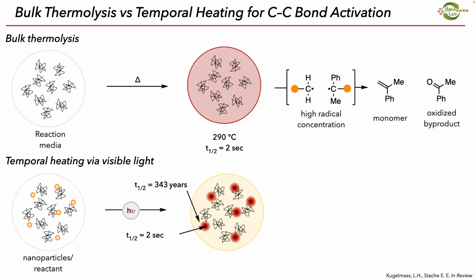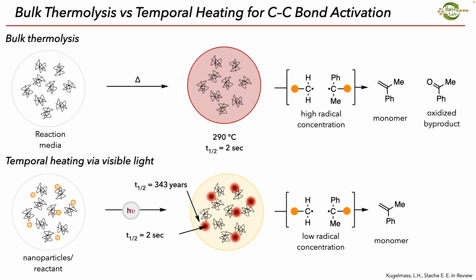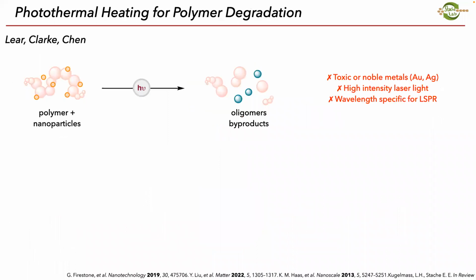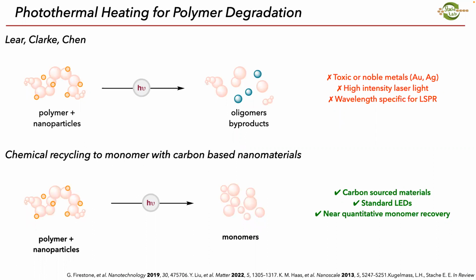And so we can spatially and temporally control low radical concentrations so that we get selective depolymerization to monomer. A few other groups have been working on this, mostly in polymer degradation. They mix the polymer with nanoparticles on a small scale, hit it with light, and get oxidized byproducts or oligomers. A lot of these cases use lasers. It's very small scale and uses toxic or noble metals. Instead, we turn to carbon-based materials using standard LEDs, light bulbs, so that we could get near quantitative